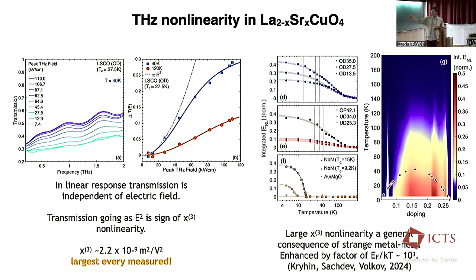And so it doesn't seem to be particularly enhanced there. It seems to be, to me, a property of the whole normal state. And so I think it has to do with interactions. A point that was made in this paper is that in strange metals, you expect that nonlinearities are enhanced by a factor of basically EF over kT. And so my feeling is that's what's going on. It's a consequence of basically linear in T imaginary self-energies.